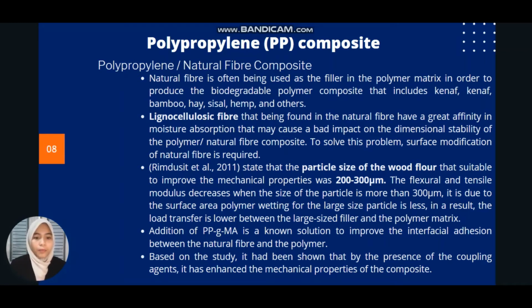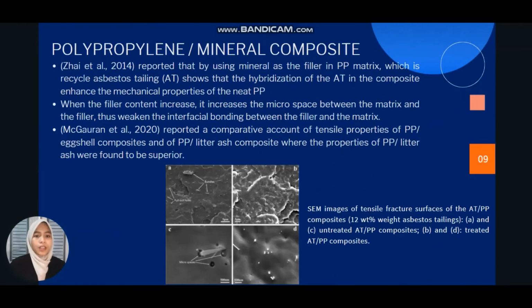And then addition of PP-g-MAH is a solution to improve the interfacial adhesion between the natural fiber and the polymer. So based on the study, we showed that the presence of the coupling agent can enhance the mechanical properties of the composite. So next is the polypropylene with mineral composite. So Zhai et al. reported that by using mineral as the filler in PP matrix, the hybridization of the AT in the composite enhances the mechanical properties of the neat PP.